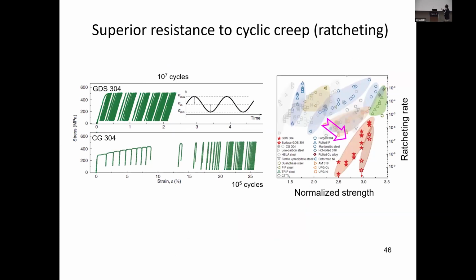And then we apply the cyclic loading, tension compression with a non-zero mean stress. This will produce this unidirectional accumulative strain. That's called the ratcheting strain or the cyclic creep. And without this kind of microstructure, the reference coarse grain 304, up to this number of cycles will produce about 25% of ratcheting strain. While for this gradient microstructure, after 10 million cycles, we only have about 2% of ratcheting strain.